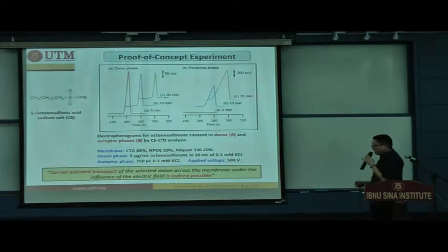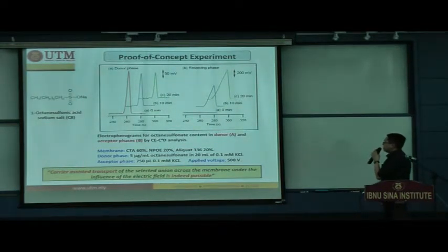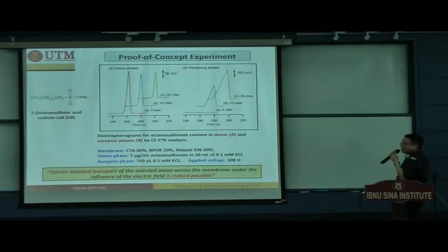For any new method, normally we are going to show you a proof of concept experiment. So octane sulfonic acid was used as the model analyte and spiked in the sample solution in 20 mL of 0.1 millimolar potassium chloride. This shows the electropherograms for the octane sulfonate content in the sample as well as in the acceptor phase. This was obtained using capillary electrophoresis with a contactless conductivity detector.